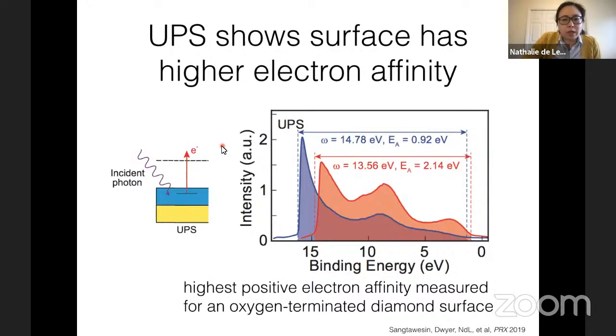We also saw, also to my surprise, that if you did ultraviolet photoelectron spectroscopy, which is a probe of the work function and the electron affinity, we saw this enormous difference in the electron affinity, by over an eV between these two surfaces. So even though the oxygen coverage was similar, you completely move this conduction band edge by about an eV.